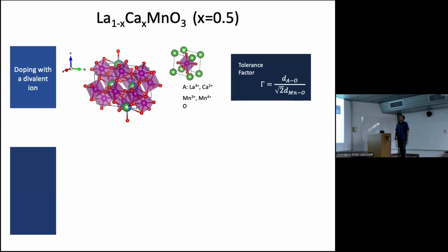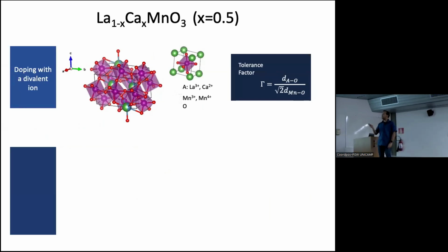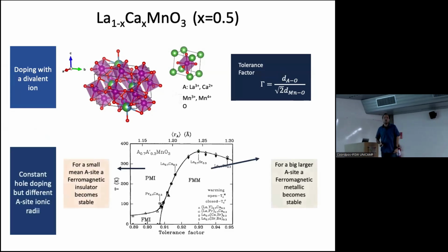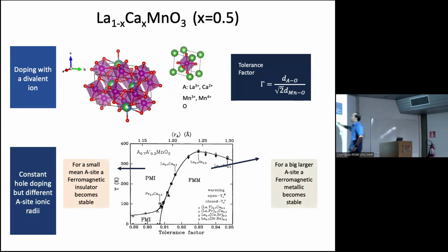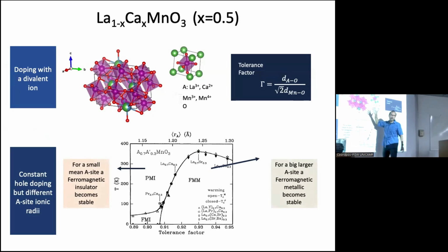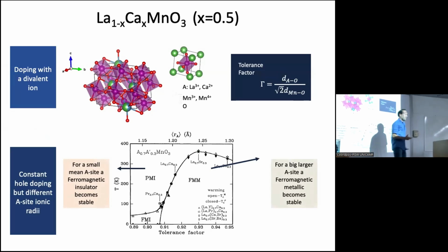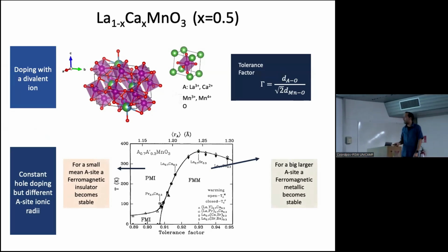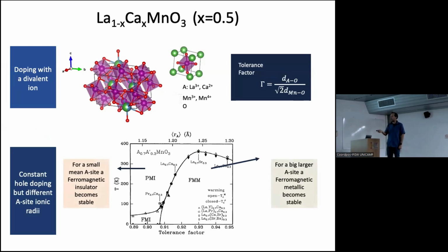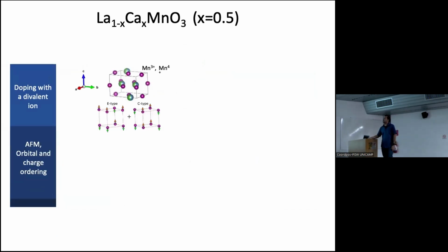Okay, so if you have something that is in between, so 0.5 of calcium here, then you basically add a way to control the material. You can, by controlling the distances between the two, which is what you do when you change the ion here, change the interactions. Okay, so that's the idea, and then you can have something that is metallic, insulator, ferromagnetic metal, depending on what ion you use.